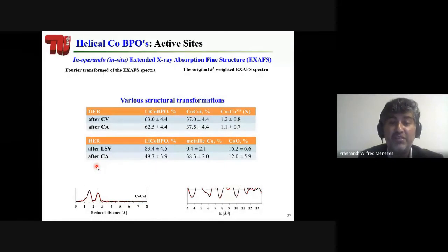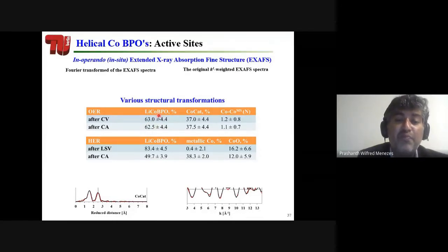What do we get? The final information we get is that when we use lithium cobalt borophosphate or any pre-catalyst in our system, it changed the structure. In here, what we see is that 63% of the structure remained, and almost 40% of the structure changed into something like cobalt oxide. Similarly, under hydrogen evolution condition, we got almost 50% of the initial product, but we also get almost 40% of only metallic cobalt, that is reduction of this material, and some amount of cobalt oxide.